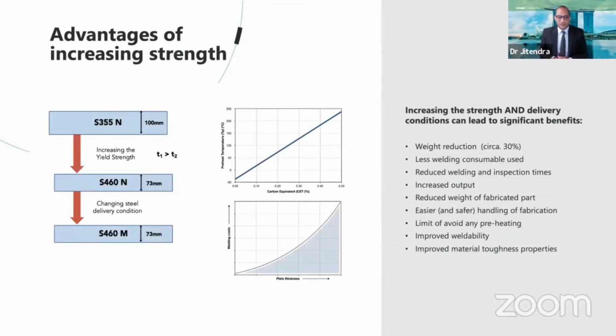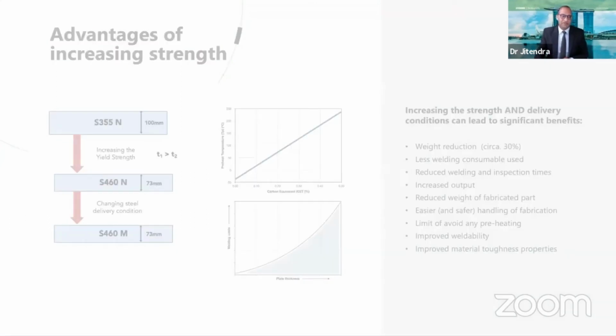If we're able to go to 460, again looking at the N and M, you can see here that we're able to go from 100 millimeter plate in an example here down to 73 millimeters. And this is the typical trend that you see: as you go up in plate thickness, the welding costs start to increase significantly. So if we're able to reduce this by going to a higher strength steel and going from a normalized delivery condition to an M, a thermomechanically rolled delivery condition, then there are significant savings to be made throughout the chain.